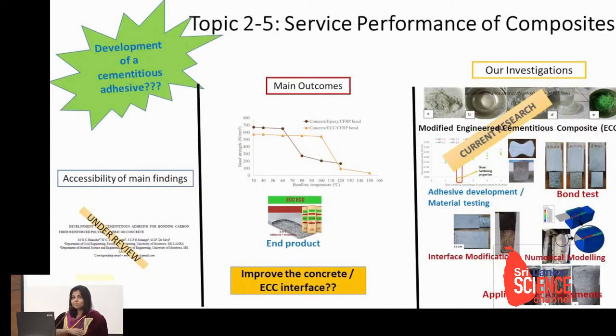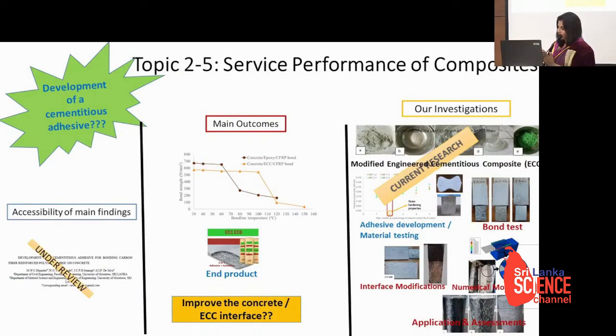Then we thought to develop a cementitious adhesive system to replace the bond between CFRP and concrete. So we started trials with engineered cementitious composites, and then we further developed it using fly ash and PET fibers after characterization of a set of possible materials. At the end of the trial series, we found the best product, applied it to the bond between FRP and concrete, and tested under ambient condition. Actually, it failed. Initially, it showed very, very low strength. And as I said, if the bond is weak, there are three failure modes. In that sense, the failure was noted at the interface between epoxy adhesive and FRP material.